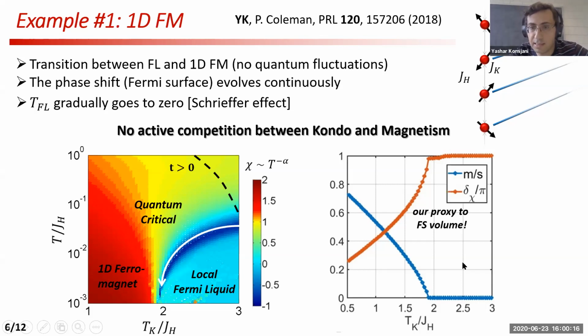This plot shows, for example, the magnetization as a function of the Doniach parameter. When Kondo is dominant, the magnetization is 0, and then at some point it gradually takes off. And on the right, you can see the phase shift that the electrons would experience. It's pi in the Kondo phase, and then it gradually goes down. As Subir pointed out, because of this geometry, we cannot really define a Fermi surface. But this phase shift is some sort of proxy to a Fermi surface volume. So we loosely interpret this as a large Fermi surface and a gradual decrease into the ordered phase.